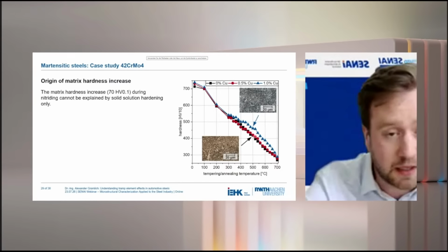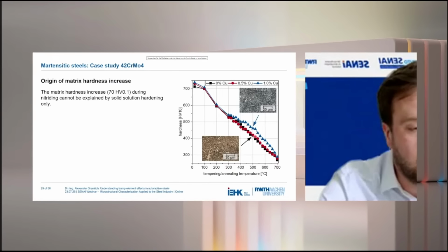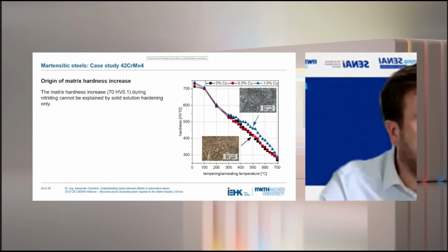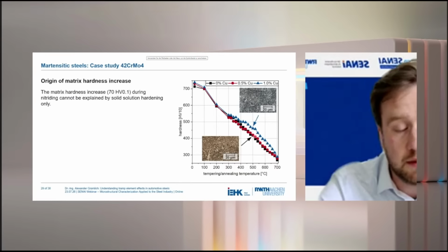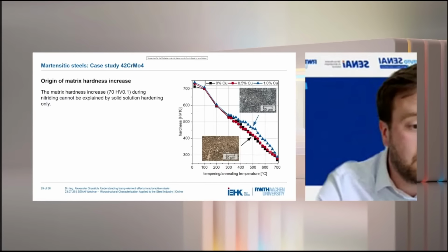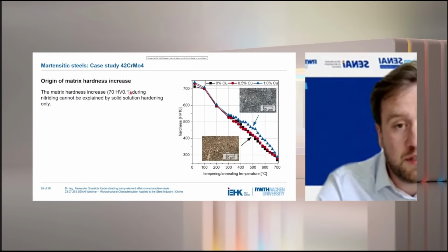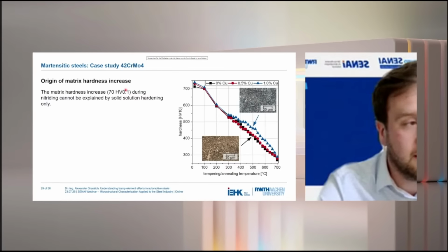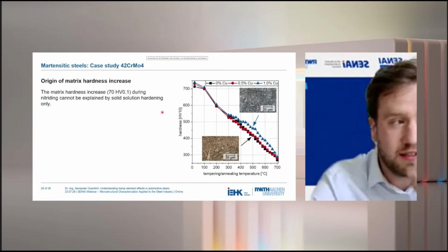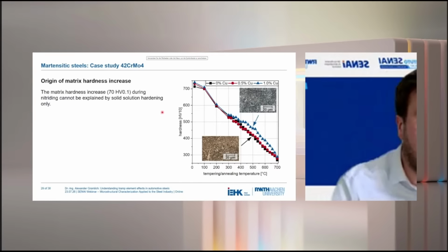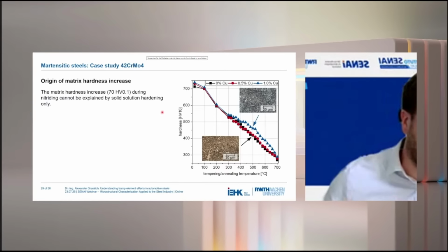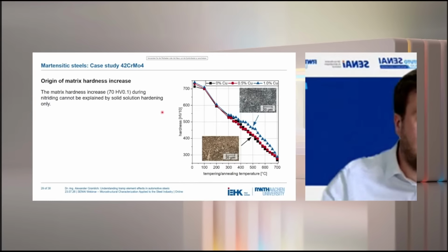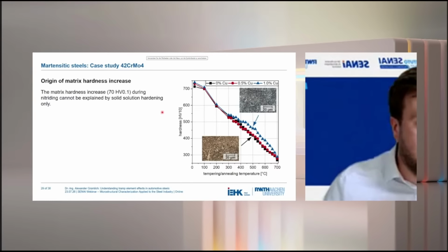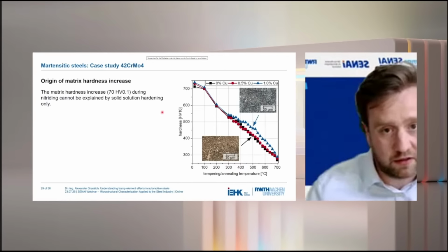The last finding, and this connects really well again back to the atom probe tomography, is the increase in hardness which we found at a certain tempering temperature. As you can see here in blue, our copper containing steel has around 70 Vickers higher hardness. However, this cannot be explained by the solid solution hardening alone, as the solid solution hardening of copper is more or less around 10 to 20 Vickers in this concentration.